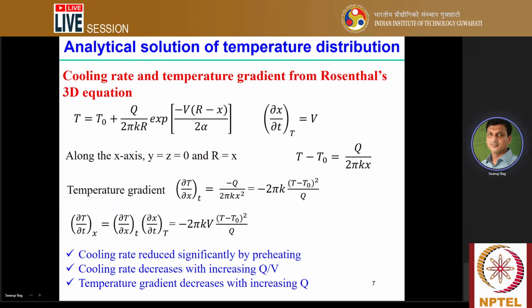Now del T by del X we have already calculated; that is the temperature gradient. We put this value in, and del X by del t is equivalent to the welding velocity. If you put it in, then we are getting minus twice pi k V (T minus T0) squared by Q. These are the expressions. So this is the analytical solution of temperature distribution, assuming the Rosenthal 3D equation.